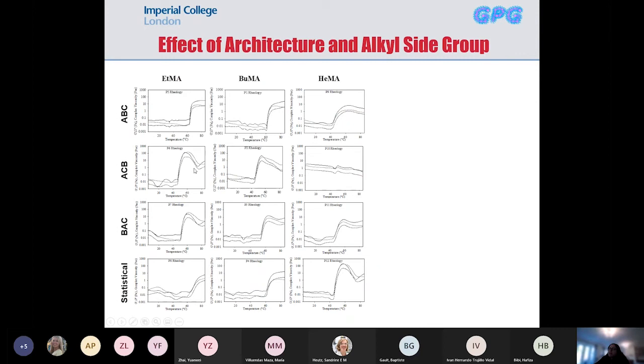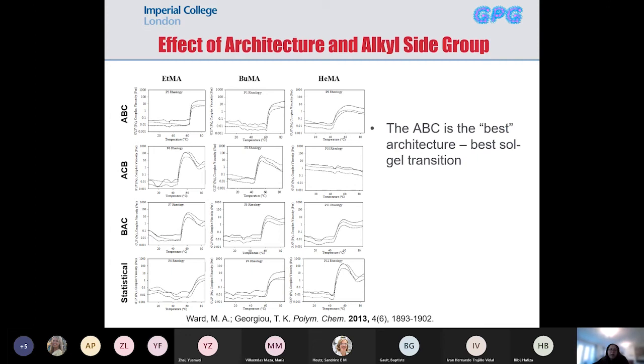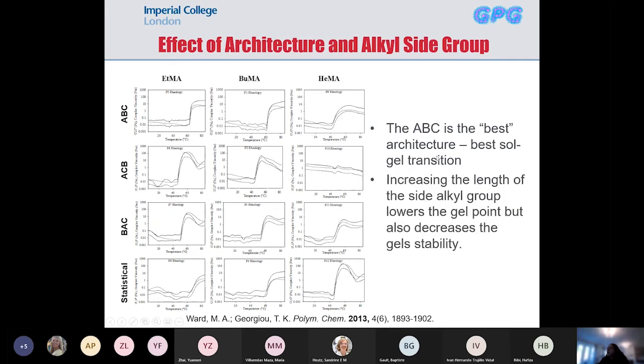So in some cases we have destabilization of a gel at higher temperatures, or in some cases we have gel at all temperatures, and this is not what we want. So in this case, we write from left to right the alkyl side group from ethyl to butyl to hexyl. And each line is a different architecture. So ABC is where we have the hydrophobic component in the middle, where for these two structures, the hydrophobic component is at an end block. And the last one is the random copolymer. And we observe that the best architecture, the one that gives us the desirable sol-gel transition, was the one in the middle, where we had the hydrophobic component in the middle, so the ABC architecture. And if you increase the length of the alkyl side group, it lowers the gelation point, but also decreases the gel stability.